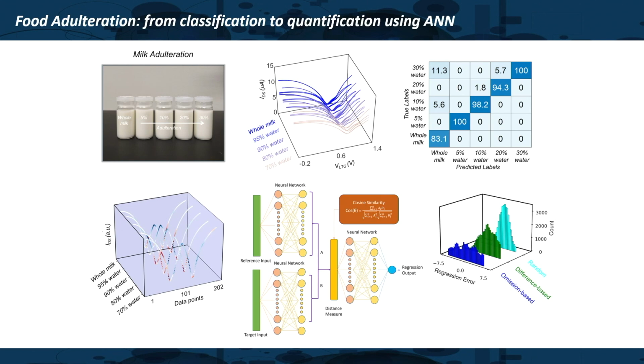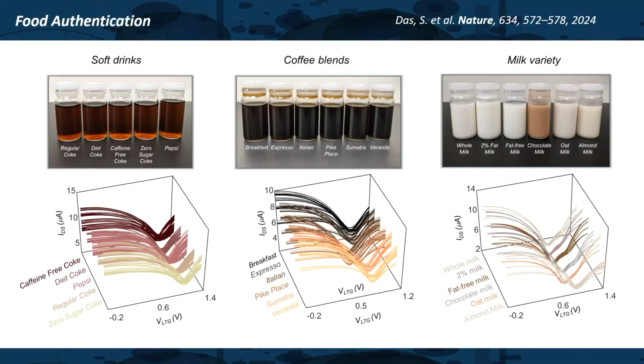But then we used the same principle. We measured a lot of devices with different milk adulteration percentages, then trained the machine learning model and looked at the accuracy of it telling you the adulteration percentage. Now, adulteration percentage is not really a classification problem, it's more of a regression problem, because you don't know whether you will be adulterating with 10% or 20% or 3.5% of water. We trained a regression-based model, and we found that it still gives you an accuracy within 2 to 3% of milk adulteration, right? The same principle, and you can actually expand it to different drinks like Coke, coffee, and milk. And one thing you notice is that it's the same exact graphene device without any functionalization.